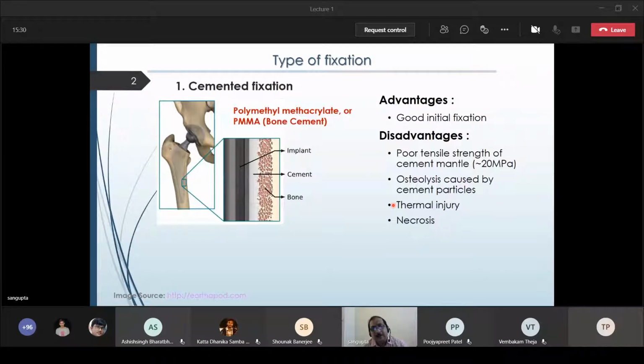It will very fast try to solidify, but it will be semi-solid like a dough. During this period, it was powder form, then we put the monomer and we mix it very hard. There is a huge thermal reaction, an exothermic reaction. As a surgeon, you have to mix it fast, and while it is still in the form of dough, you have to push it into the prepared hole, then place the implant in the desired position, and then let it solidify.